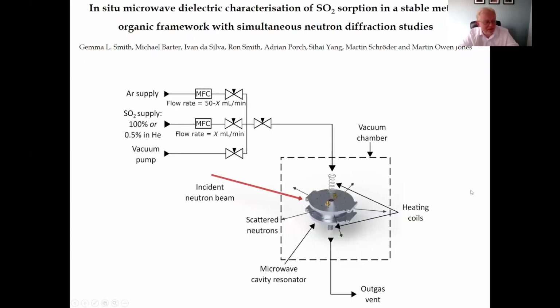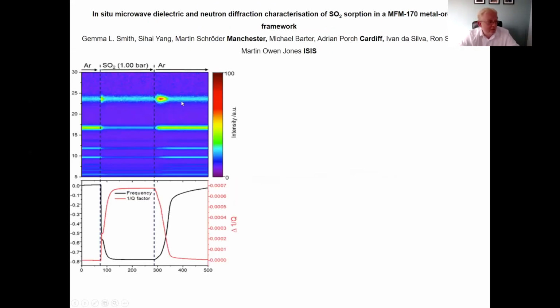Another thing we've developed is a microwave resonator for looking at the dielectric properties of materials. I won't go into too much detail about why we've done that. What it does allow you to do is this: this is the structure of our material, and this is the dielectric response. And as we put SO2, this is the same material that I talked about earlier, the SO2-absorbing MOF from Manchester, as we put SO2 onto the sample, you see this crystallographic change, and this corresponds to a big change in the frequency of the dielectric properties.